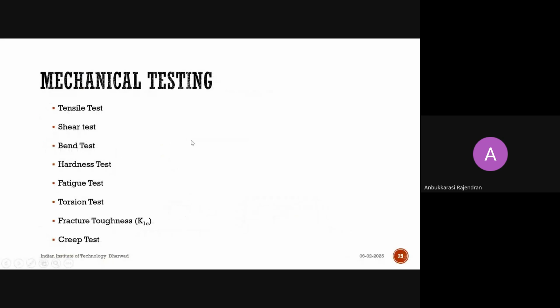Yesterday during Ajay's presentation, someone asked about finding out the shear strength or micro bonding strength of some coating, right? If I'm correct, there was micro tensile one thing, and second thing is some interface layer was there. They wanted to test the strength of the interface layer, right? Okay, so that's what I understood. So the interface strength, if you want to measure it, you can try to go for the peel-off test.